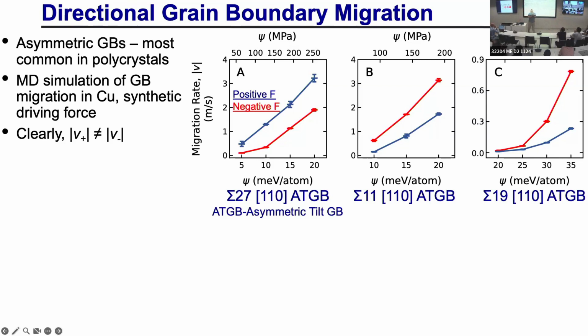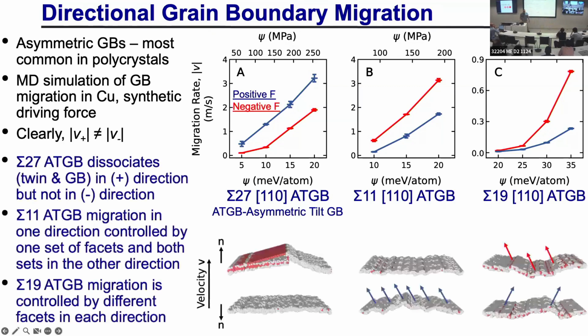Now, once we start getting those results, we say, okay, let's look at the structure of the boundary as it moves. Okay, so what I'll show you are some structures of the boundary when it's moving this way, and I'll show you the structure of the same boundaries when they're moving that way. So in this particular grain boundary, the sigma 27 boundary, when it's moving this way, it splits into a twin here and another grain boundary here. So this is faceted, but it breaks into this pair. When it's going the other way, it does not break into that kind of pair. So the structure of the boundary moving that way is different than the structure moving that way. Okay, so it's not surprising that they have different mobilities because the structures are different.